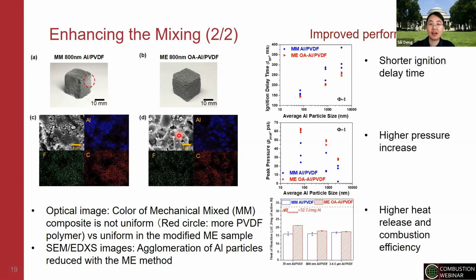And we also tested the combustion and ignition performance in the traditional constant volume combustor. And you can see that the ignition delay time gets shorter when we use this micro-emulsion technique. And also we achieve a higher pressure increase, which indicates a higher combustion temperature and a larger gas generation from the combustion of the energetic materials. And also from this bomb calorimetry, we can see the total heat release. Because all the materials are the same, all the improvement in the heat release is due to the manufacturing technique.